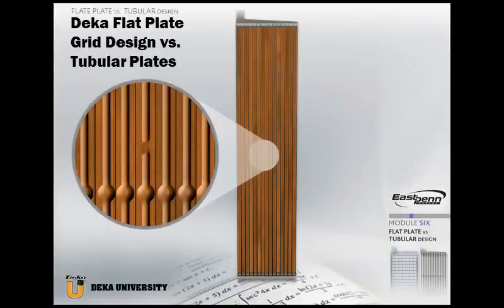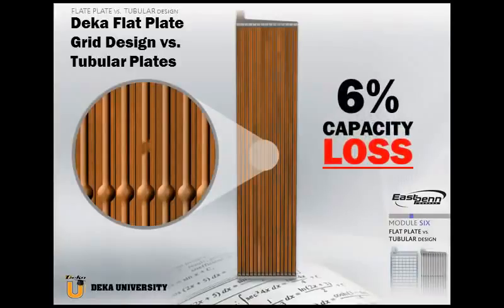Since there are normally 15 spines in a plate, the corrosion of one spine can result in up to a 6% capacity loss. As the battery ages, it is possible for corrosion to occur on several spines, resulting in serious capacity loss and a reduction in service life.